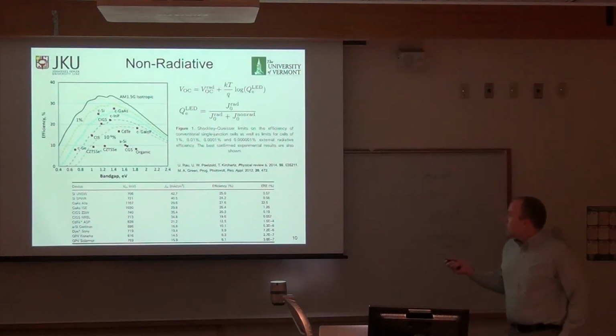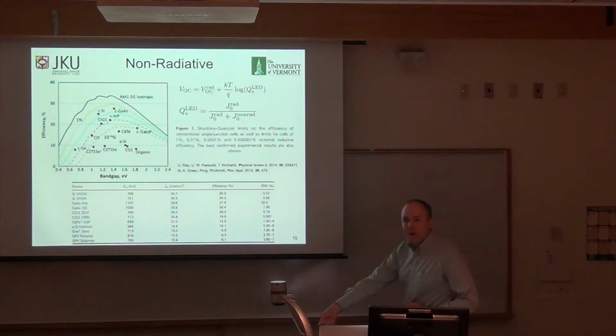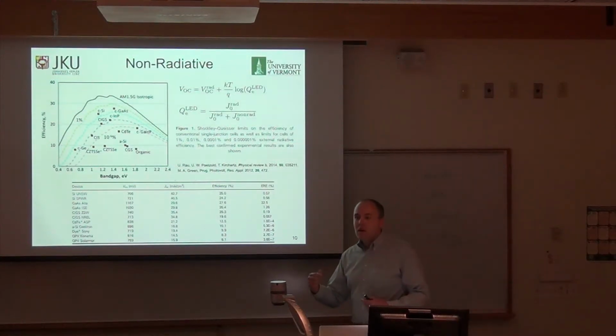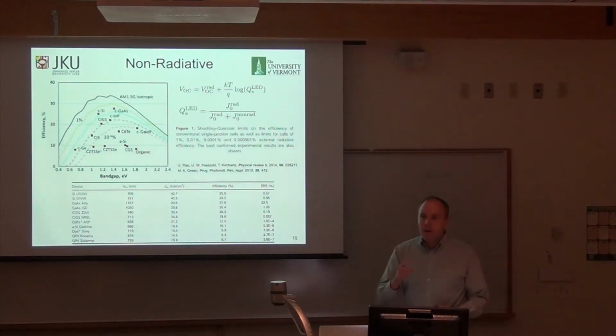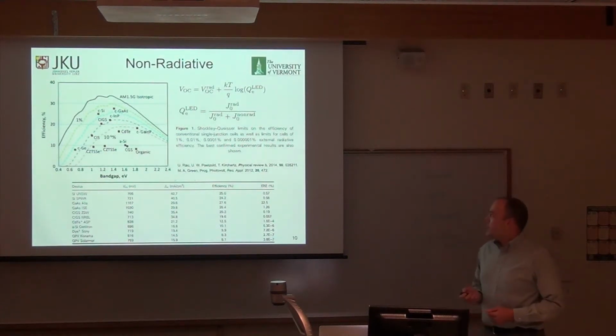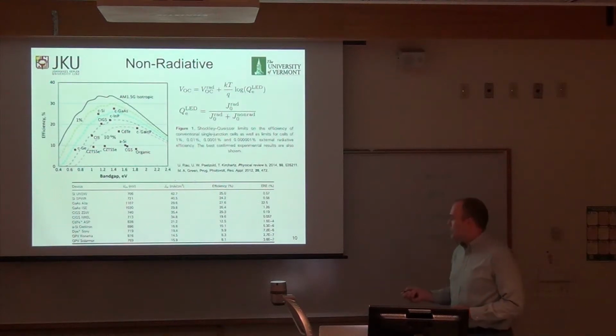This comes from an additional loss in the VOC related to the quantum efficiency of what we would call an LED. If you take your solar cell and drive it in forward bias, you inject current into it. Ideally, every electron you inject will recombine with a hole and emit a photon. But that doesn't happen—you have recombination losses through non-radiative processes, and that can be quite significant. In fact, your radiative recombination efficiency for a lot of these processes is something like 10 to the minus 7. So almost no radiative recombination happens.